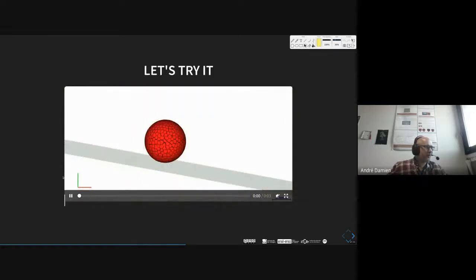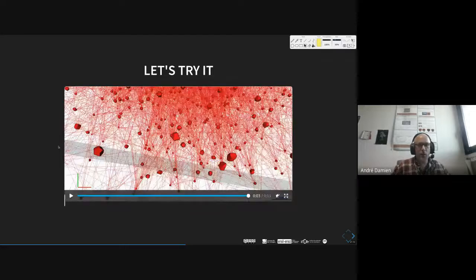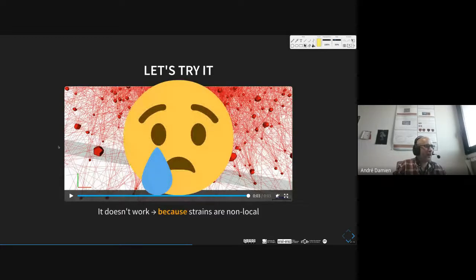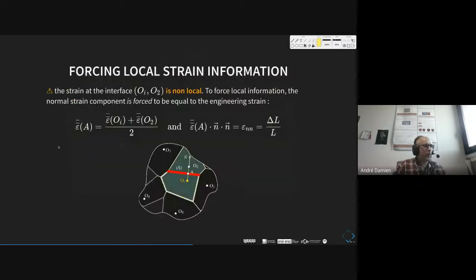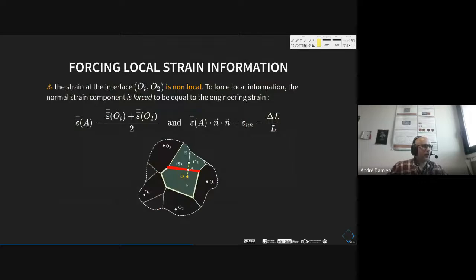So this is my first try, and as you can see, it's not very good. What we miss here is that the strains in this case are non-local. What do I mean? It means that it's important to compute the original displacement field in the local frames of the discrete element. If we don't do that, of course, we are not able to manage high displacement and high rotation. So this is an important thing to do. And this feature was not present in the original DLSM method.